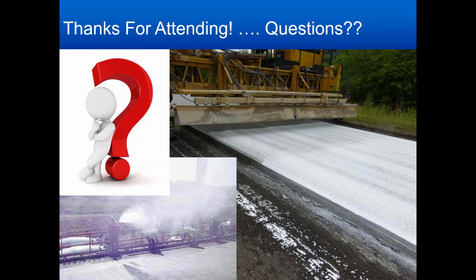Thanks, Mark. One other question here that's come up, Tom, I'll throw it back to you. Since many of today's concrete mixtures use fly ash or slag cement, which retard the set time, would liquid admixture retarders be recommended as well? Good question. There does need to be some caution with mixtures that are blending cementitious powders and liquid retarders together, since the concern is that they may over-retard the mix and increase the potential for plastic shrinkage cracks.